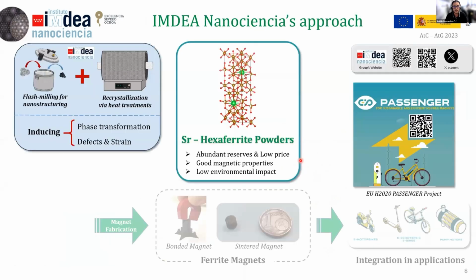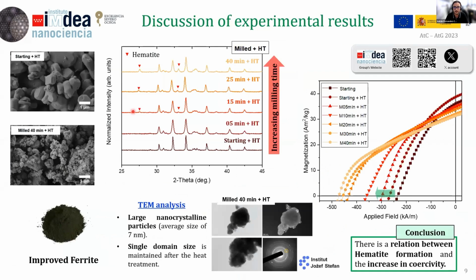So we can see now the improved magnetic properties of the strontium hexaferrite. As we increase the milling time, the formation of the hematite is induced, and we manage to increase the coercivity of the initial powder almost twofold. So from here on out, we make a relation between the hematite formation and the increasing coercivity in this system.